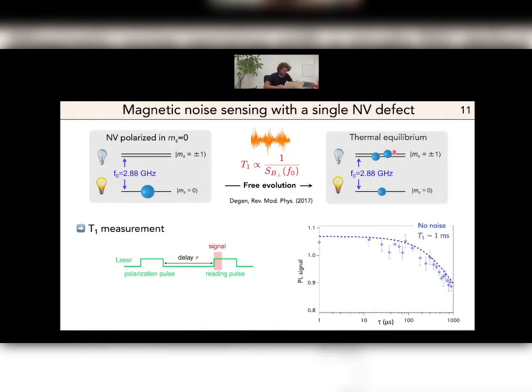This is a typical result that you can get for a single NV defect without any magnetic noise in the surrounding. You end up with a T1 time of about 1 millisecond, which is essentially limited by phonons in the diamond matrix. If now you apply noise in the vicinity of the NV defect, you can see that indeed you shorten the T1 time here by one order of magnitude. This technique is called relaxometry.